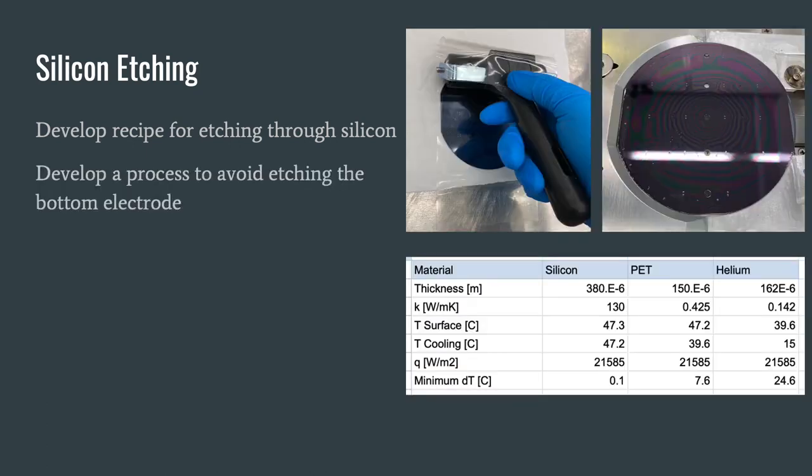The idea is to apply dicing tape to the backside of the wafer. I thought about how the idea can fail and performed some simple calculations to verify that the tape won't melt, the adhesive won't melt, and the sample wafer will not overheat. I also know from experience that the samples are never hot after etching. Although optimistic, I was thrilled when it worked on the first try. Fortunately, this process works every time thereafter, saving me time and the customer money.